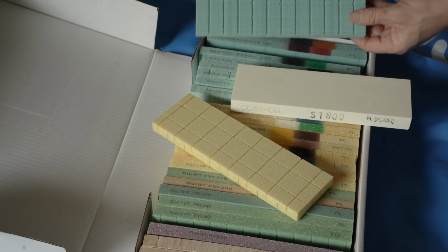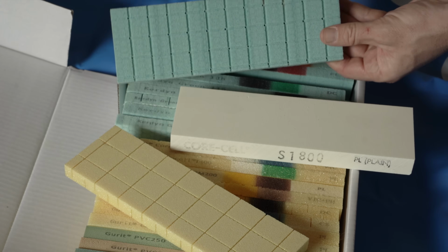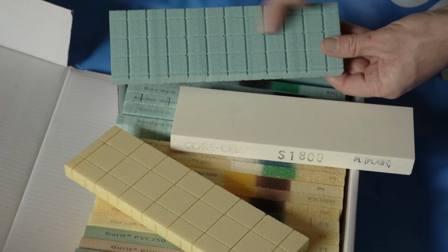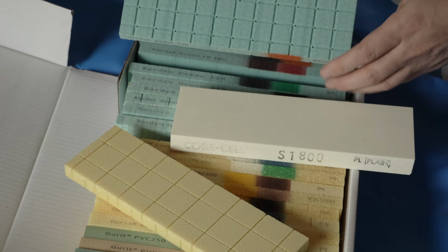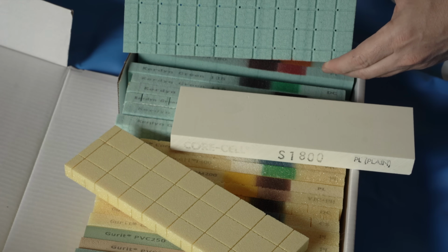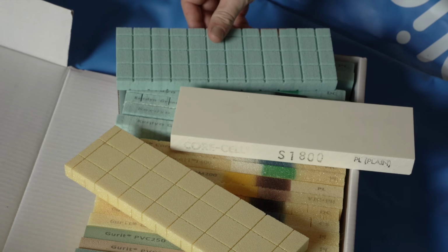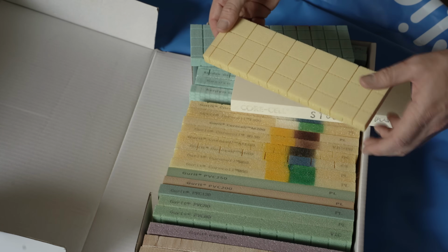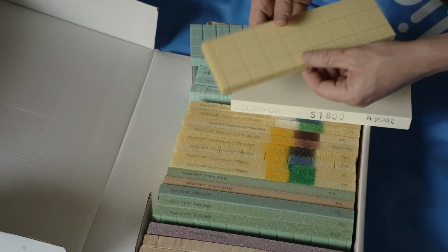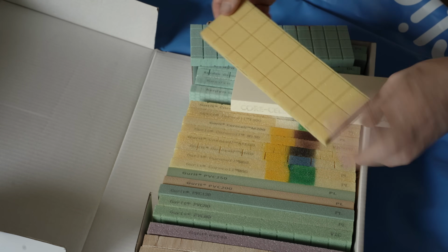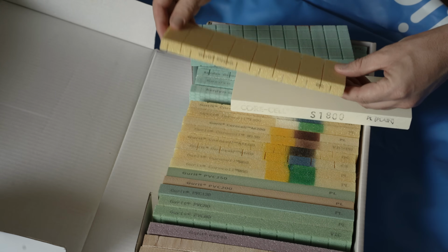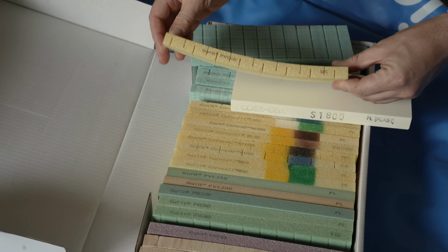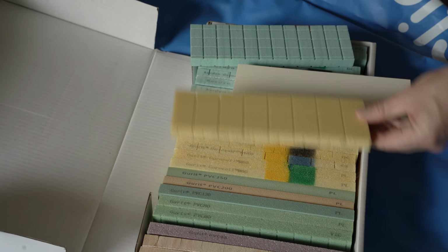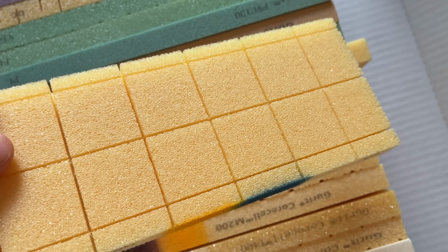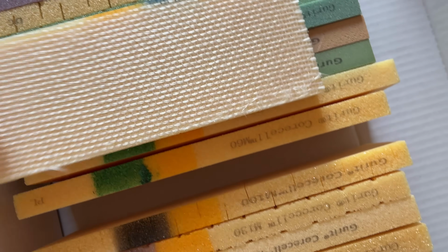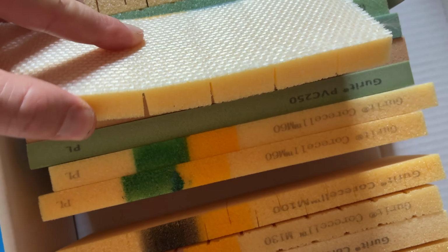You can also get resin infusion optimized core, here with channels both sides to let the resin quickly travel along the dry, pre-positioned sandwich of fabrics, and also holes perforating the core so resin can travel top to bottom and wet everything out. Finally, you can get scored foams to aid bending and conformity to shapes. It's offset so that the cuts on both sides don't meet and cause the cubes to separate. You do need to keep in mind though that the slots will end up resin filled, which is dead weight. This method saves the need for thermoforming or for a fabric scrim to keep the blocks together.